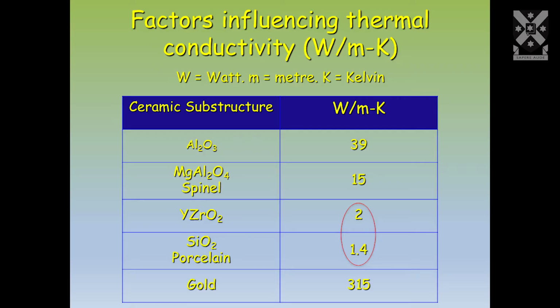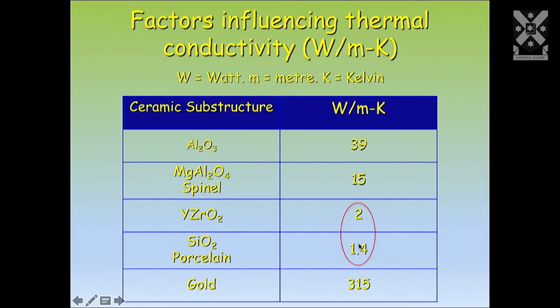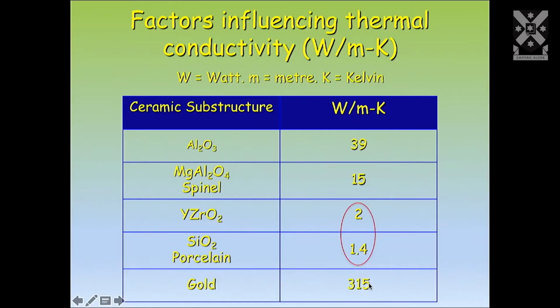And the first thing that we realized as the group looked at this was that the thermal conductivity, that's the rate at which heat is transferred through a material, of the veneering porcelains here was very similar to the zirconia. And that has huge implications to the cooling when it comes out of the furnace. If you look at metals, 315 compared to that, they will lose the heat at a much more rapid rate. And likewise, you see the aluminium oxides.